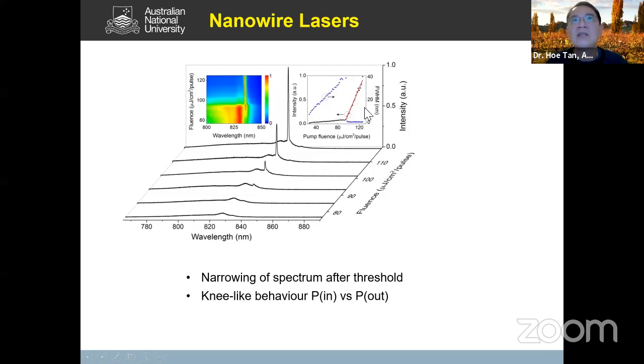And as you can see on this plot of output light versus pump power, there is a kink-like behavior, a classic sign the device is lasing. Another indication that the device is lasing: if you look at the full width half maximum of the spectrum, it increases with excitation power until it hits a threshold, and then it drops suddenly. Okay, so these are two proofs that the nanowire is lasing.